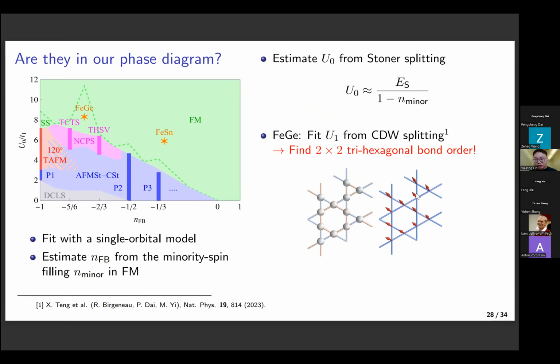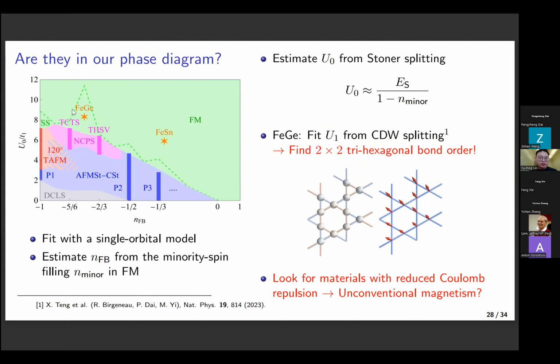That is, in addition to the ferromagnetism, we can also find a charge bond order where the strong bond will form a hexagon and a triangle. And this 2x2 trihexagonal bond order has been known as the CDW for the 2x2 order in the kagome Van Hove singularity. So we are actually really proposing the relevance of our phase diagram in the practical materials. So as Pengcheng has asked previously, right now we think that the current materials like iron tin and iron germanium are all in a strongly repulsive ferromagnetic regime.